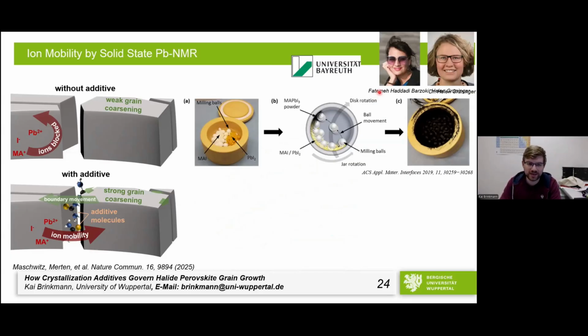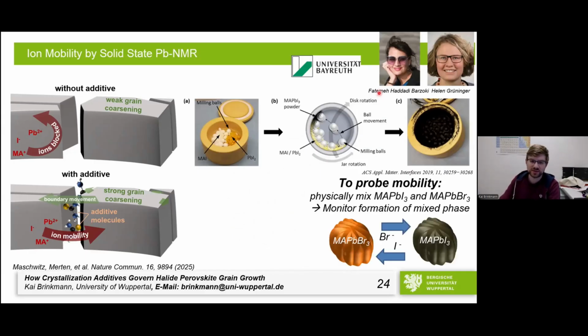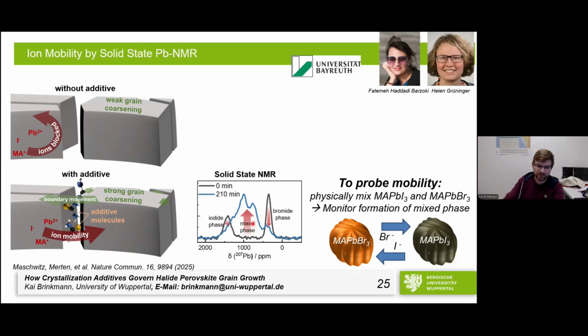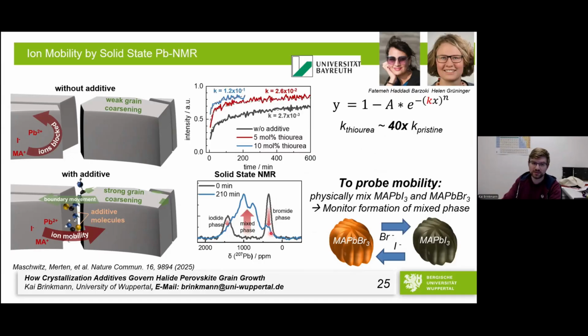What they did is they used a ball mill to mill perovskites. And what they milled is a perovskite, the methylammonium bromide perovskite and the methylammonium iodide perovskite, both with and without the additive inside. Then they mixed it and measured solid state NMR during the mixing process. And then they can basically track how the mixed phase emerges and how the single phases decrease. And doing this makes it possible to put a number to ion migration by probing the mixed phase. So seeing how the mixed phase emerges over time.